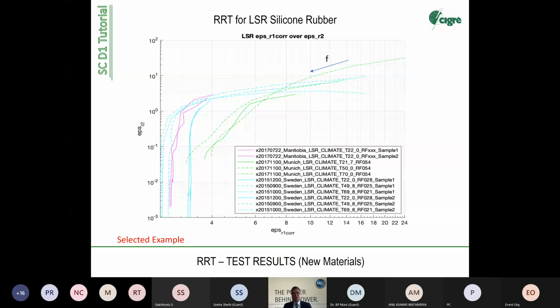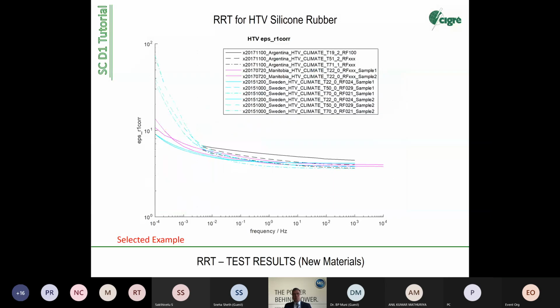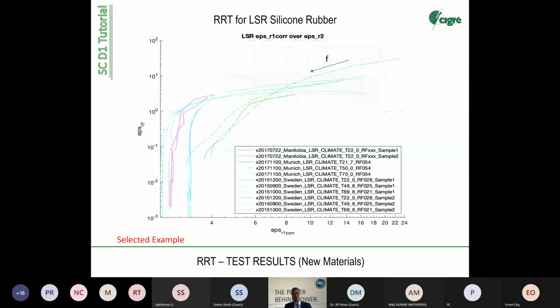Here, what you can learn from here, so the scatter seems not to be so high anymore, but you can see a clear tendency. So all test labs for this material show more or less the same dielectric fingerprint. Here we investigated an HTV material. We have to say this material is filled in comparison to the liquid silicone rubber. Liquid silicone rubber has no aluminium hydroxide filler. So it's a pure material, more or less pure material with low amount of interfaces, actually theoretically with no internal interfaces, but also they use some kind of silica to get a mechanical property. So also these materials have some kind of interfaces, but a low amount.